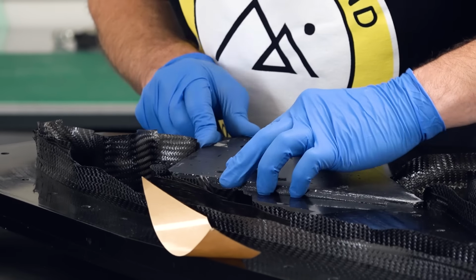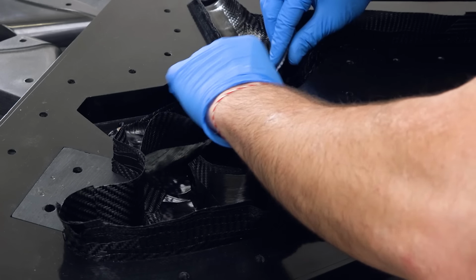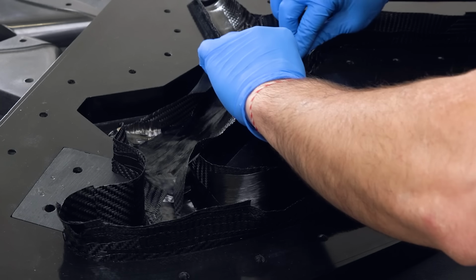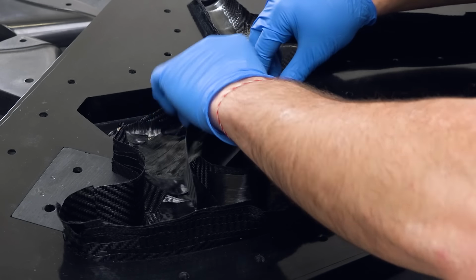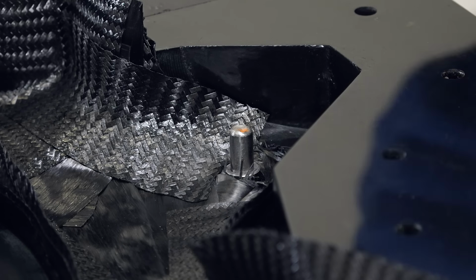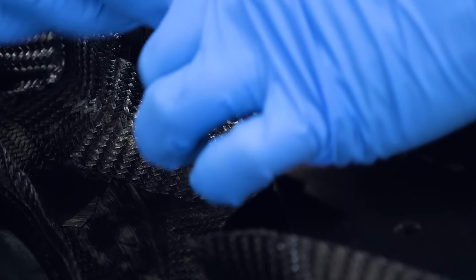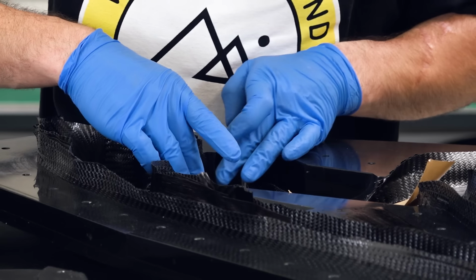This laminate is overspecified for the build and will almost certainly be reduced by 2 or 3 plies after this first proof of concept has been tested. Stressed areas such as the head tube, suspension mountings and bottom bracket will have more plies that stagger into the main tubes, forming a taper to spread the stress concentration.